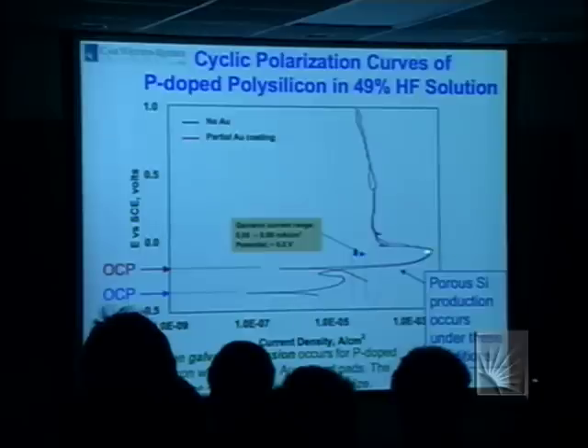And there are enough surface steps, surface sites on porous silicon that there was hope that you could get a direct conversion of electrons into photons. During that work, folks discovered that you could produce porous silicon electrochemically, and if you did that by working in this current range, and that's just the range that is occurring when we make this galvanic couple in an electrochemical cell.